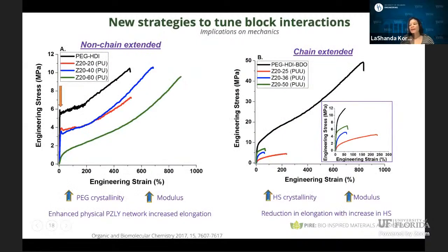So how does that impact mechanical properties? That's one of the most important things here. For our non-chain extended systems, again, engineering stress versus engineering strain, the PEG crystallinity is really driving the overall mechanics of the system. As the PEG crystallinity increases, you have a higher modulus, which correlates well to what we see on this graph, where the green curve, which has the highest overall peptide fraction, you can start to see a reduction in the modulus, but a higher extensibility in the systems. And this is really driven by the fact that you have this really strong network system.